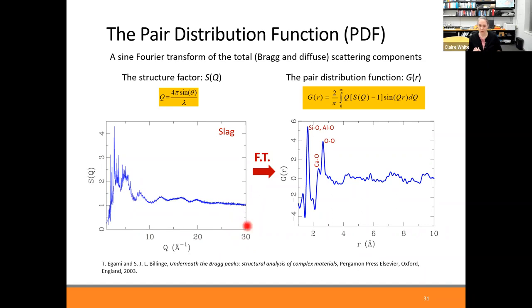You can cover more of momentum transfer, which means when you Fourier transform the data, you end up with better resolution in real space. And so what's shown over here is a sample that has both diffuse scattering, so scattering from the amorphous component in the material, and also these spikes are the Bragg peaks, the crystalline contributions. So you're Fourier transforming both the disordered component, if it's present, and also the crystalline contributions, and you're ending up with your pair distribution function over here, which is a histogram of all atom-atom distances in your material. And so it shows you bond lengths, and then it shows you longer range distances between atoms.